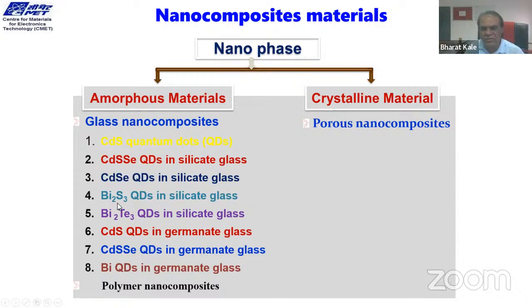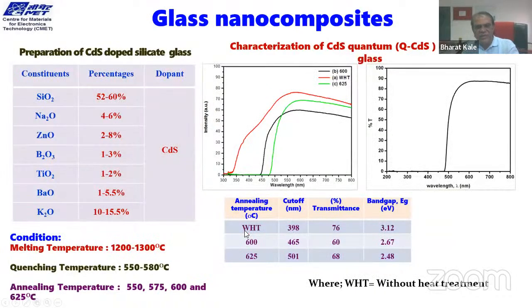CdS quantum dots, CdSe quantum dots, bismuth sulfide. It took us almost 10 to 12 years to develop this technique, and we are growing any kind of quantum dots in the glasses. This is the glass nanocomposite with CdS quantum dots, cadmium sulfide quantum dots. You can see initially in the glass, if there is no growth of crystal, then it is 350 nanometer.